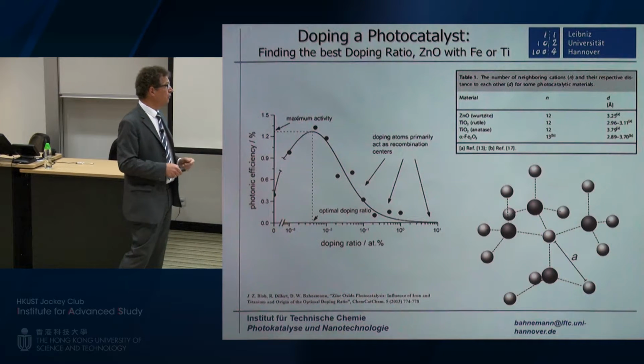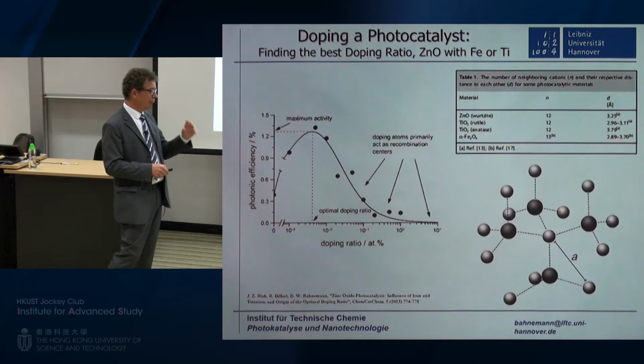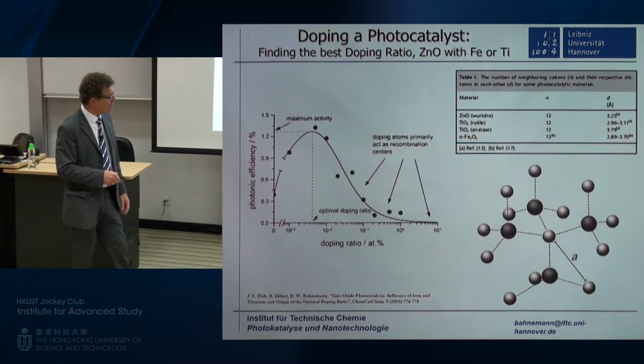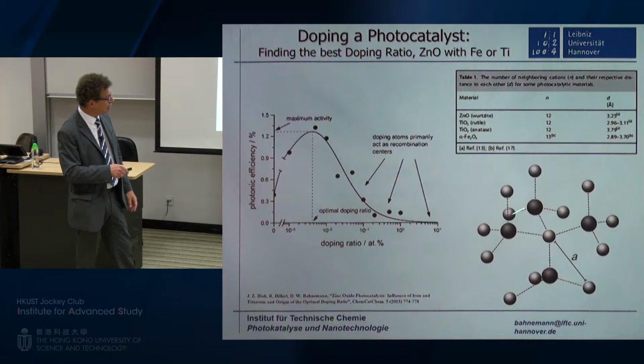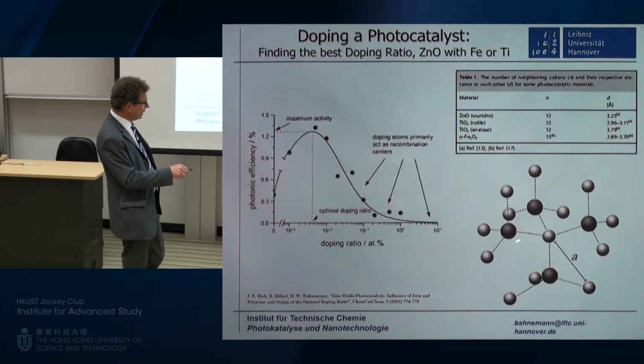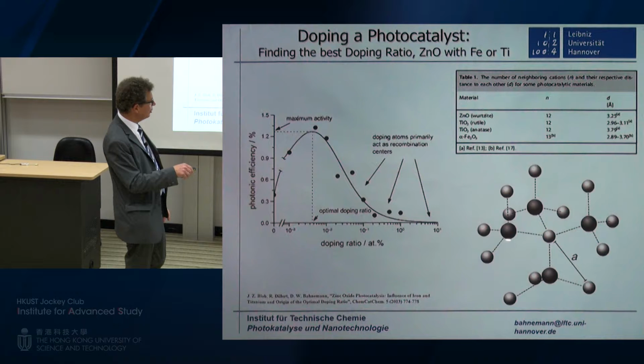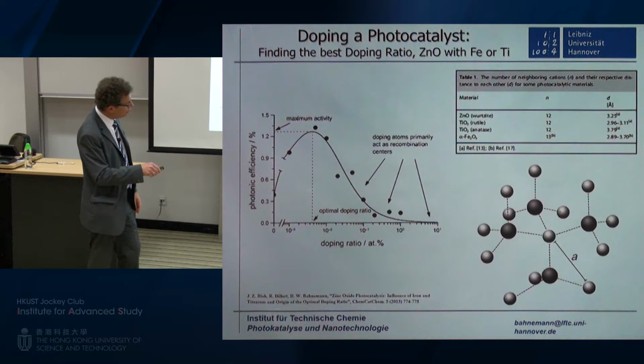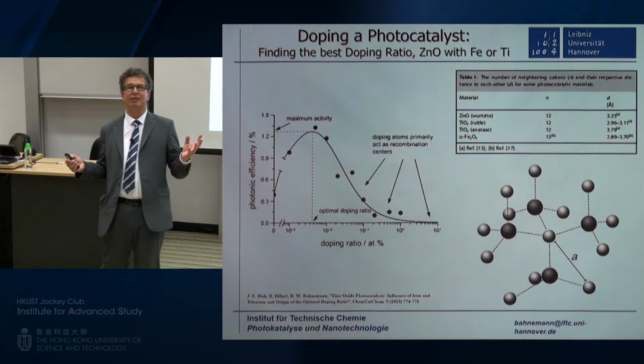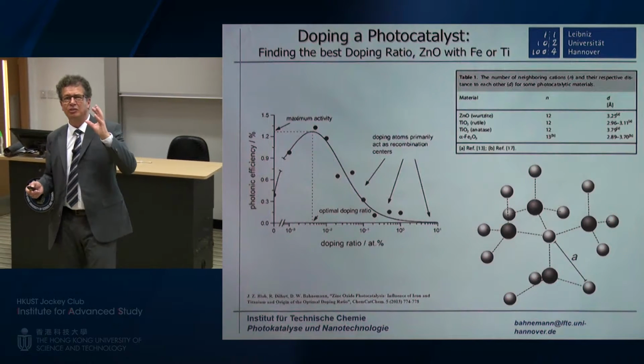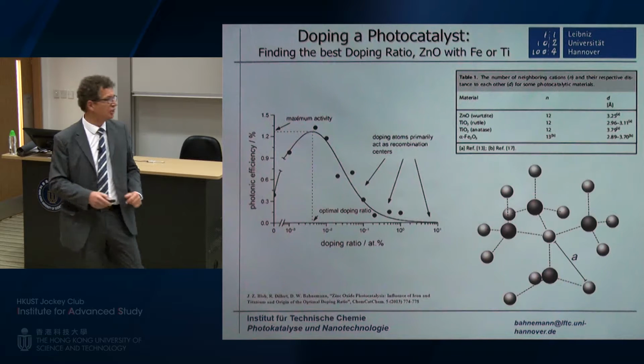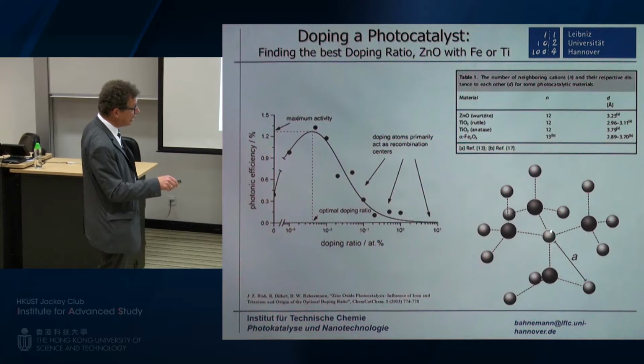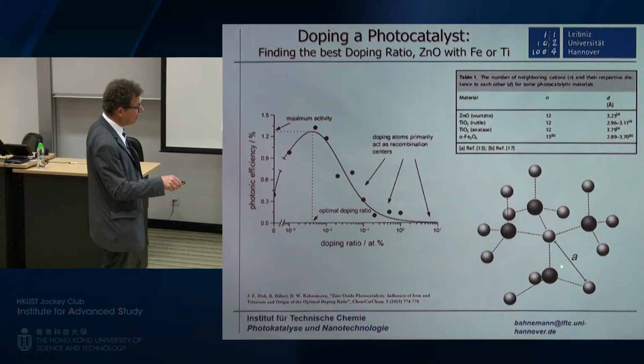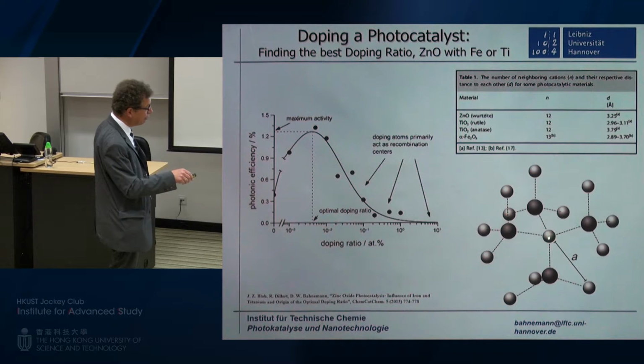And the second thing is we felt, well, maybe if you put too many doping ions in the particle, what they could do, if you, for example, put, this is the zinc oxide structure, the wurtzite structure of zinc oxide. These are the zinc cations, these are the oxygen anions. Let's assume you replace one zinc cation as a nearest neighbor here at this distance A to this zinc ion by a dopant. And let's assume this was too much. Now this dopant acts as a recombination center, recombining the electrons that are in here and the holes which are trapped in the oxygen.